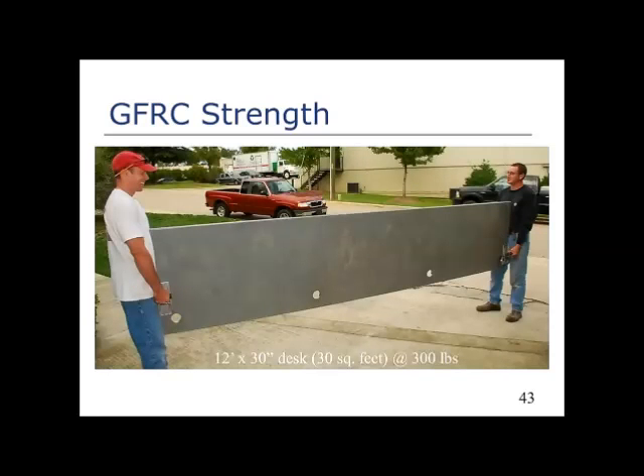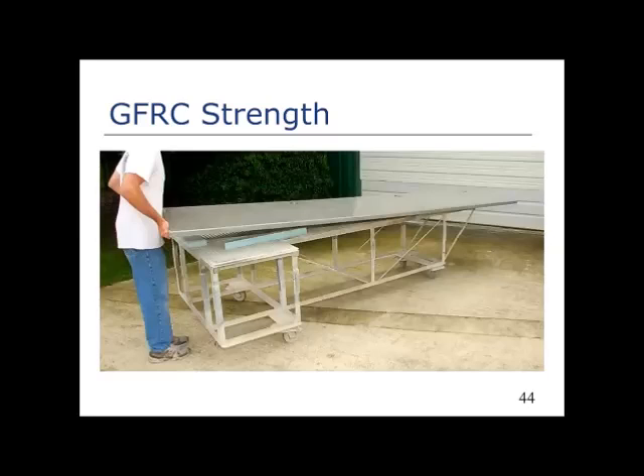So in this case, this is in one of my old offices. We needed a desk, and so I made a 12-foot long desk. It's 30 inches wide, so it's 30 square feet of concrete, and it only weighs 300 pounds. So here we have 30 square feet of concrete that's being handled very easily by 2 people, and they actually posed for this and held it up for a couple minutes. Dave wasn't smiling at the end of that, but you can see how it's not difficult to handle a very large piece of concrete, and even when it's set down, it can be picked up from one end, and it's still very flexible. No cracks. Even after 5 years of heavy use, it had 0 cracks or anything in it.